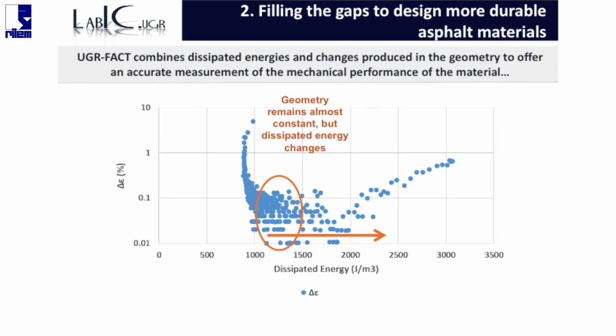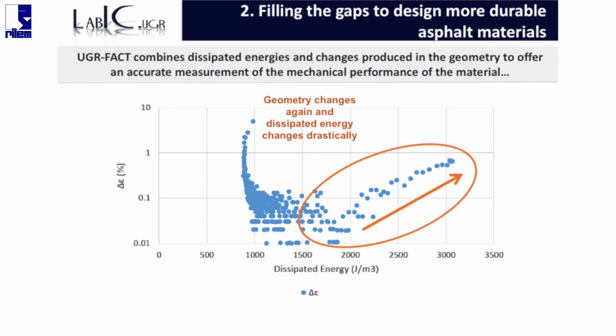Then we are going to have a second part where the change in geometry becomes very low and the dissipated energy starts to grow. So that means that we are in the damage initiation phase. And in the end, in the last part, geometrical change starts to grow again, and also dissipated energy grows drastically. So that means that we have the damage propagation stage.